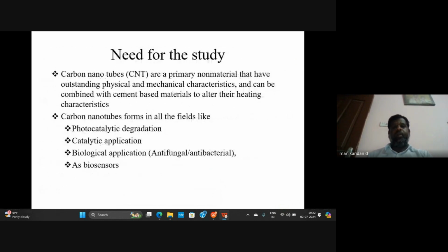the CNTs. Objectives: to synthesize helical multi-wall carbon nanotubes by CVD deposition and purification, to determine the percentage carbon yield, and to characterize the final product of helical multi-wall carbon nanotubes using XRD, FESEM, EDAX, TEM, porosimeter, Raman, TGA, and growth of CNTs using CVD techniques. Need for the study: carbon nanotubes are primary nanomaterials that have outstanding physical and mechanical characteristics.